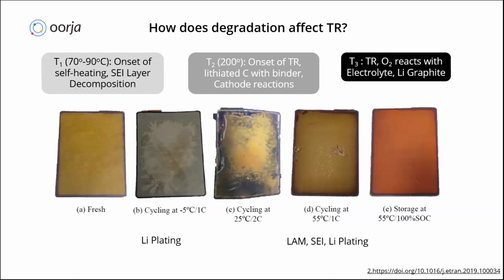Now, what happens is that when the cell starts aging, like 300 cycles, 500 cycles, or 1000 cycles, and so on, due to the aging itself, the T1 and T2 temperatures start coming down. Earlier the cell could withstand, let's say, up to 90 degrees Celsius thermal load; it may now stand just 70 degrees thermal load, and after that some self-heating reactions will get started. That means the cell will be more susceptible to thermal runaway as it gets aged. How much it will be affected depends on how the cell is being used, how it is getting aged, and what dominant degradation mechanisms are present in that cell, which depends on the usage of the cell itself.